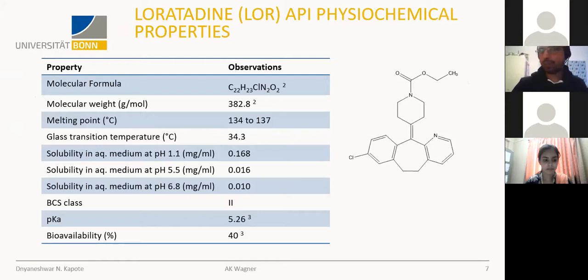Then I will introduce the API, which is my model drug. It's loratadine, a weak base having pH dependent solubility. The solubility you can see at pH 1.1 is 0.168, so we can say it is soluble at lower pH, but as the pH increases, the solubility drops. That's the problem: when you take the medicine, it gets dissolved at stomach pH, but when it goes to the intestine, it gets precipitated and is no longer available for effective action.